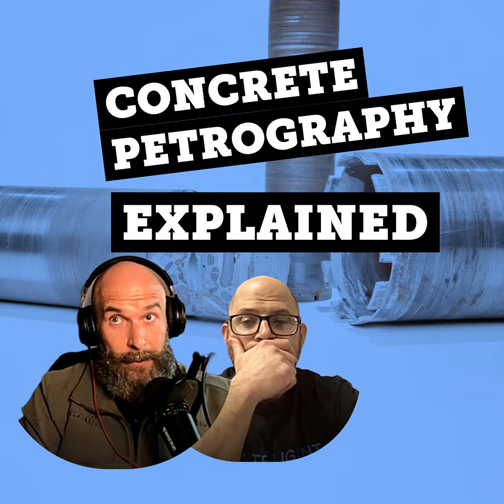Now, the reason why it's light gray, it's getting brighter, is it has some things in it that will hold on to electrons. It'll start charging. If there isn't anything in that space, it won't hold on to electrons, it won't charge, and all we'll see is black, hence we have the pores. Now, what we do is we take this sample, we zoom in on it, and then we use the backscatter electron microscope. It has something called an energy dispersive X-ray analysis tool, which allows us to collect some of those electrons and identify what we're actually looking at, either using a line method or an averaging method or a point method.